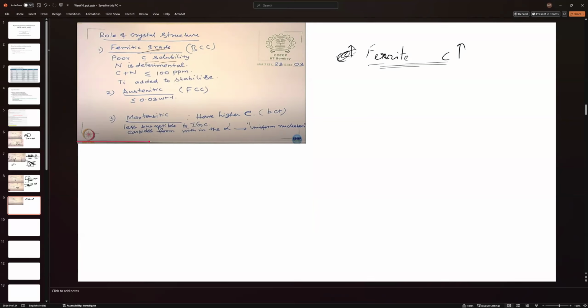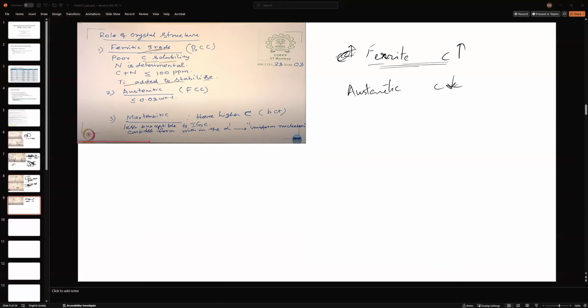Here the solubility of carbon is low. It doesn't want to stay in the BCC structure, so it will move toward the grain boundary. So we usually add titanium or other stabilizing elements to prevent IGC. Austenitic steels: here the carbon content is low. But I think we didn't mention anything about diffusion.